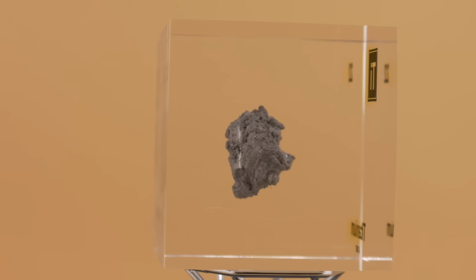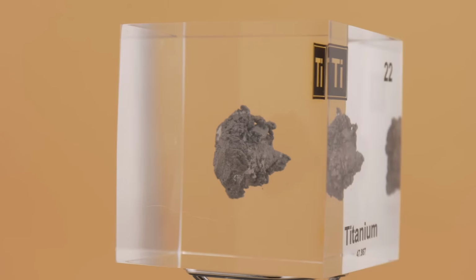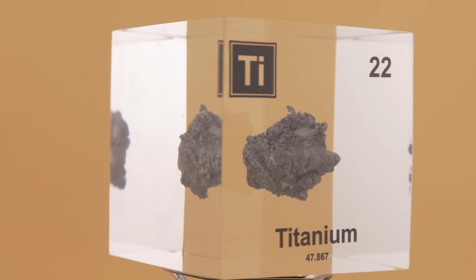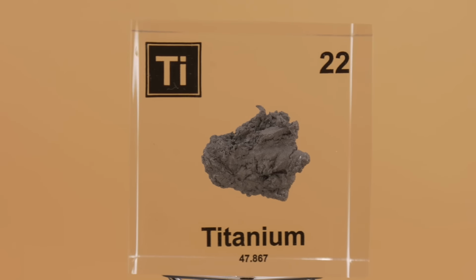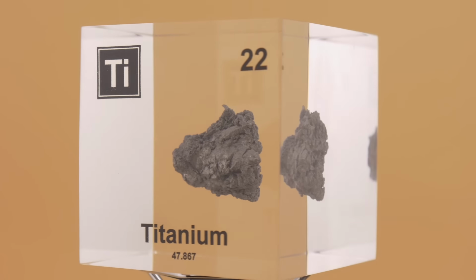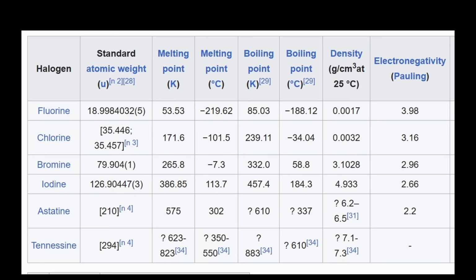Now similarly, at around 1200 degrees Celsius in air, titanium will rapidly oxidize, and at 610 degrees Celsius in pure oxygen, it will ignite into titanium dioxide. It's also very reactive with halogens, like chlorine, fluorine, etc. At high temperatures, for instance, titanium will combine directly with hot chlorine gas around 550 degrees Celsius to form titanium chloride.